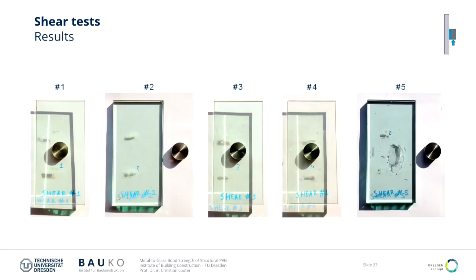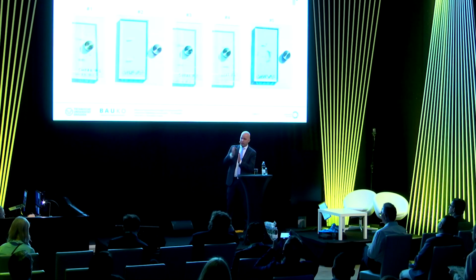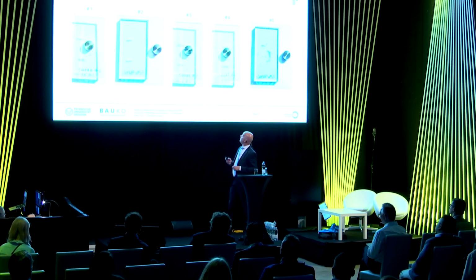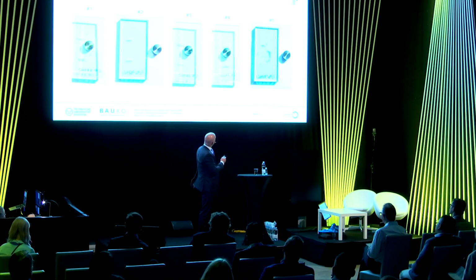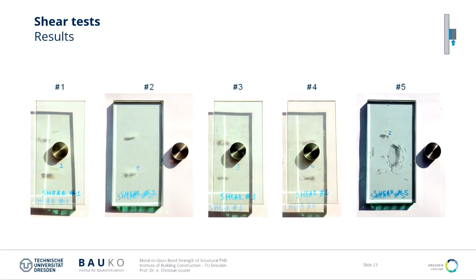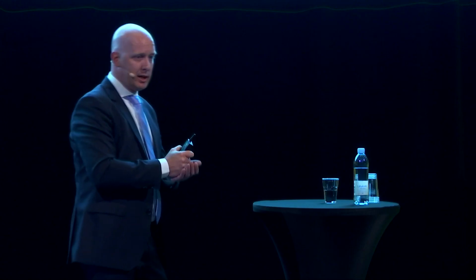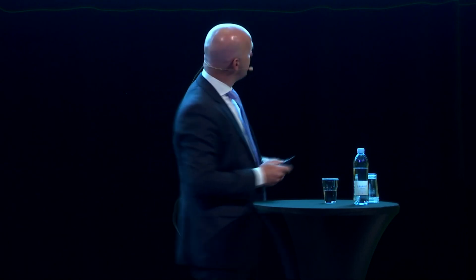These are the specimens after the test. So we tested 5 specimens in this case. You can see that for specimens 1 to 4, we have adhesive debonding at the glass side. And for specimen 5, we even pulled out the glass there. So we plucked the glass, so the top layer of the glass is completely ripped off from the glass specimen. So relatively high adhesion there.